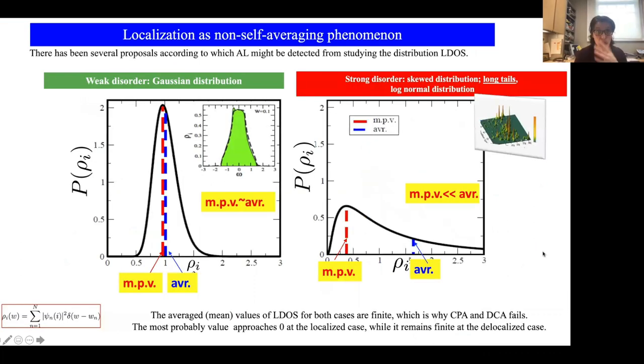There has been more insight from other theories into this behavior, where it has been suggested that Anderson localization might be detected by looking at the probability distribution function of this local density of states. To demonstrate that there is some truth to this, here on the left I'm plotting the probability distribution function of the local density of states at weak disorder. And we can see that the most probable value, the peak of this distribution, and the average value coincide. However, once you go to strong disorder, we see that the average value is here, while what you would measure experimentally, the most probable, typical value, is here.